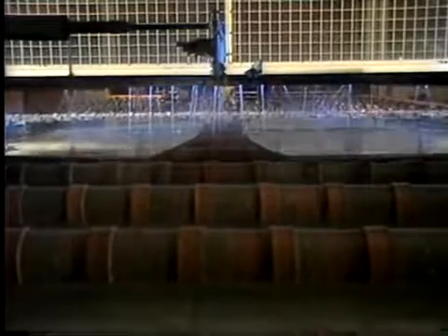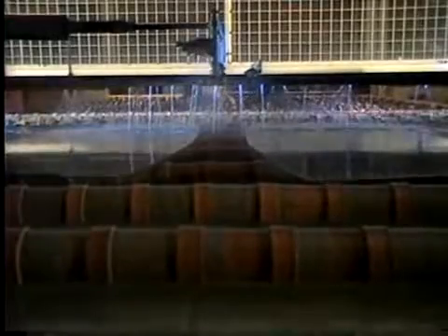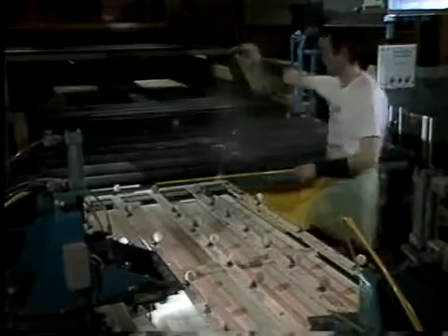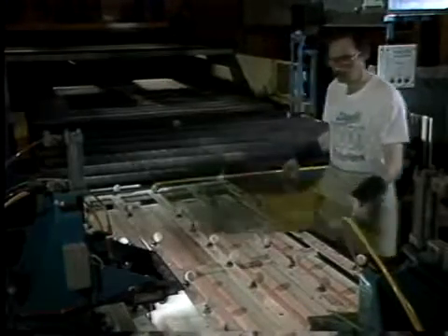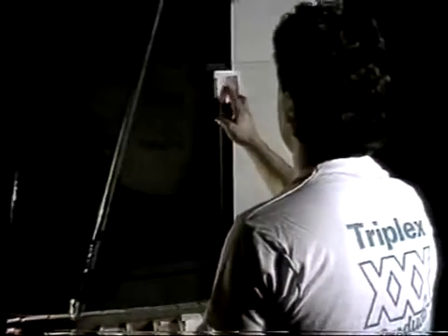Alternate glasses are cut as inners and outers, one slightly bigger than the other to compensate for the difference in curvature when stuck together with the plastic sandwich. The glasses are curved as a pair using a sag bending process, where at 600 degrees Celsius they bend under their own weight into a mold. The thin plastic interlayer is added in between the two pieces of glass, and the package is squeezed together before being baked in a high-pressure furnace or autoclave for 1.5 hours. Each panel is then checked for quality under special lighting conditions.